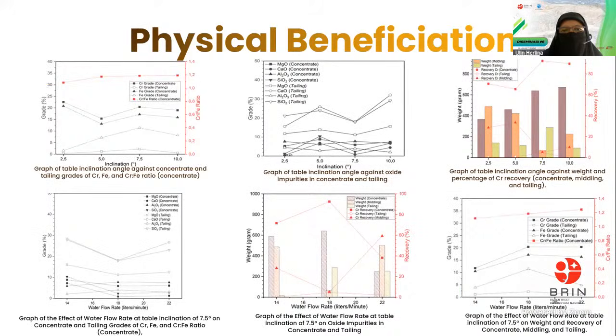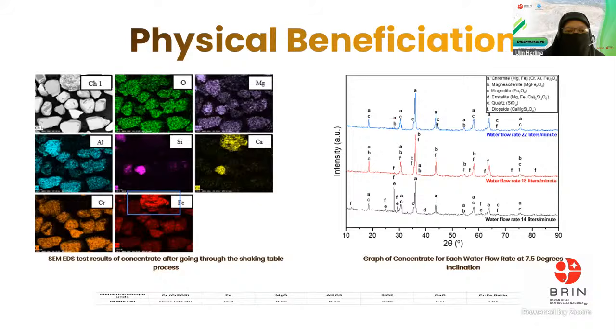This is the result of physical beneficiation. I use two parameters in this physical beneficiation. First is the inclination, and the last is the water flow rate. The chromium to iron ratio is improved in this physical beneficiation, at inclination 7.5 and a water flow rate of 18 liters per minute.